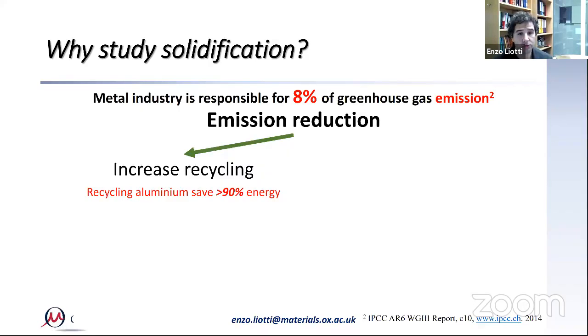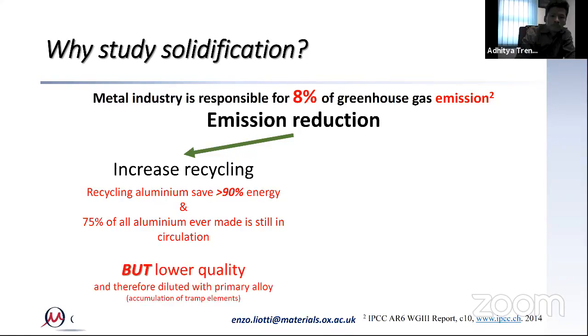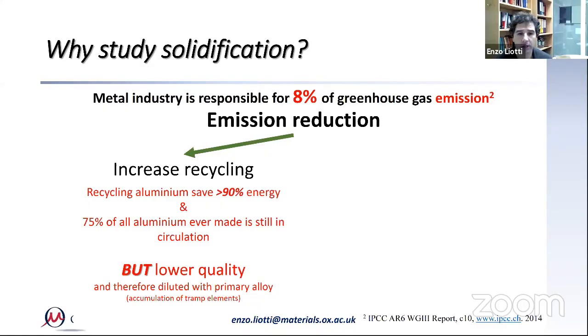And this is quite interesting for metal alloys, because recycling aluminium saves 90% of the energy. That's not very big news. And also 75% of the aluminium around is still in circulation. However, every time you go through the recycling cycle, the quality of the material you are recycling decreases. And therefore, still nowadays, industry dilutes secondary alloys with primary additions to basically bring back the quality of the material to an acceptable standard. And this has all the disadvantages of having to extract primary material to produce enough quality.